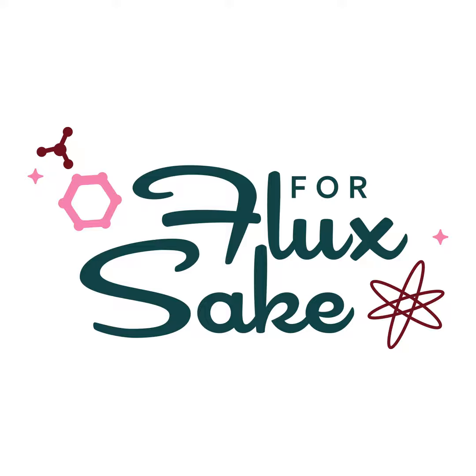A eutectic is when you take two materials and they've got a natural bottom melting temperature, but when you combine them, they create a chemical reaction that creates a temperature that melts lower than either of them could naturally achieve. Now, the first thing I have to say is the vast majority of people in ceramics use the word eutectic wrong. You hear people often use the term eutectic to just refer to fluxing, like silica melts at a high temperature and they'll say, oh, well, the fluxes are creating a eutectic. Wrong, absolutely incorrect. That is just fluxing. A eutectic is taking that minimum temperature that flux would get you to and pushing it even farther than the material naturally can. It's a special chemical reaction.